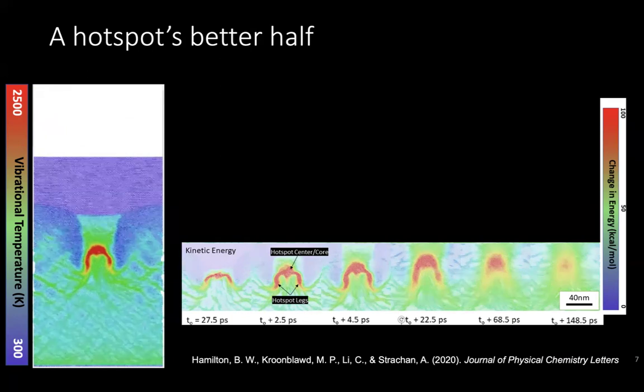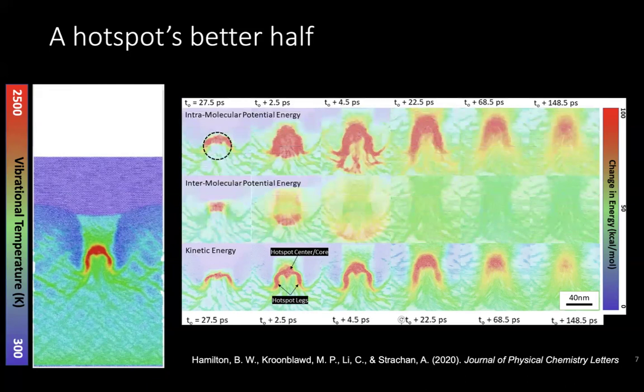Now, hotspots are localized energy. You can localize energy as temperature, which is basically kinetic energy at these high temperatures. But you can also localize it as potential energy. And what we found is that in these dynamical hotspots, there's more energy localized as potential energy, so molecular distortions, latent potential energy, than what it is localized as temperature. So temperature doesn't tell you half of the story of the hotspot.